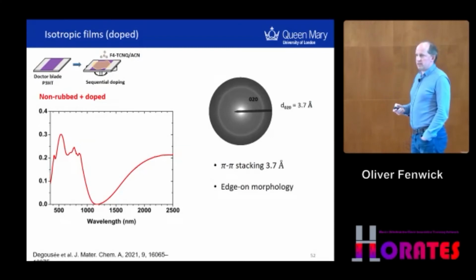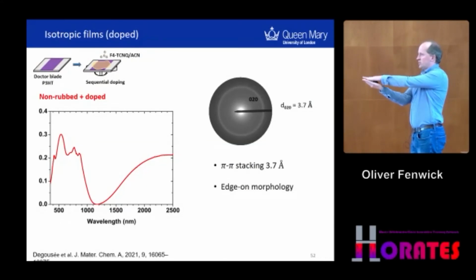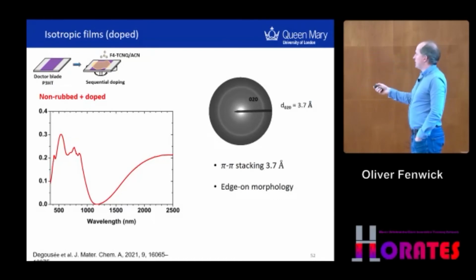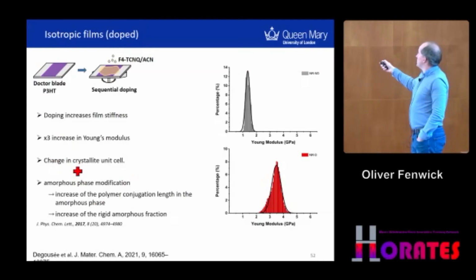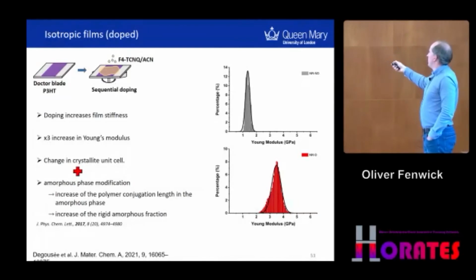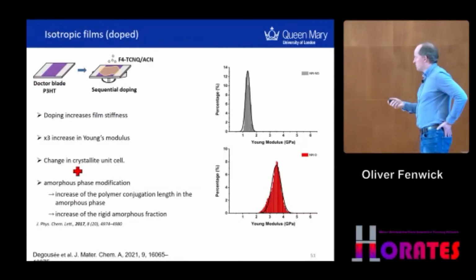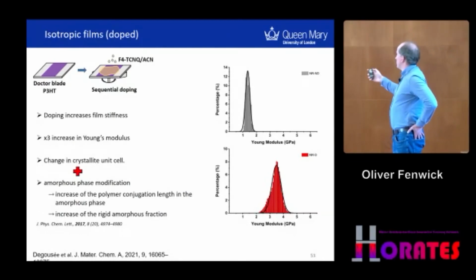An edge-on morphology is generally better for charge transport, but for thermal transport, the pi stacking direction is improving, and that direction is out of plane. So it isn't going to be picked up by in-plane thermal conductivity measurements. That may be limiting the thermal conductivity that we see in the aligned films when we measure them. Also, compared to the undoped case, and in fact compared to all other films, we now have a much stiffer film, about 3.6 or so gigapascals Young's modulus. So this is something we'd associate with high thermal conductivity.